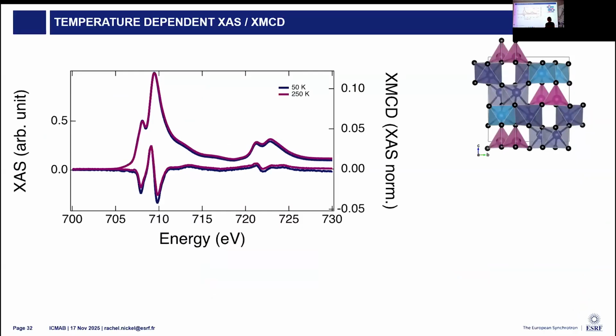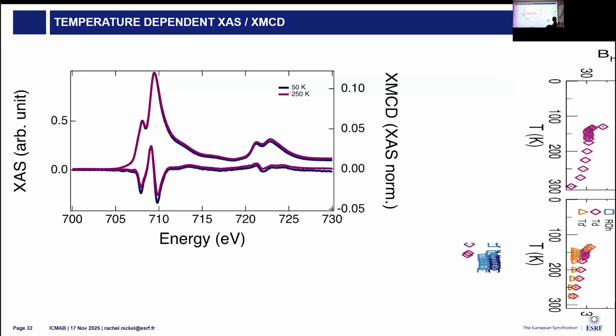So we went to our standard workhorse technique with XAS and XMCD to see if we could get any information about what's happening to the electronic structure. Because Mossbauer gives us the local environment, we know that either the iron is changing or something in the iron-oxygen hybridization is changing. If we look at the XAS, this is done at 50 and 250 Kelvin. There aren't significant differences. And this is a little bit of a problem, because we know from the Mossbauer that there are changes that should be visible.